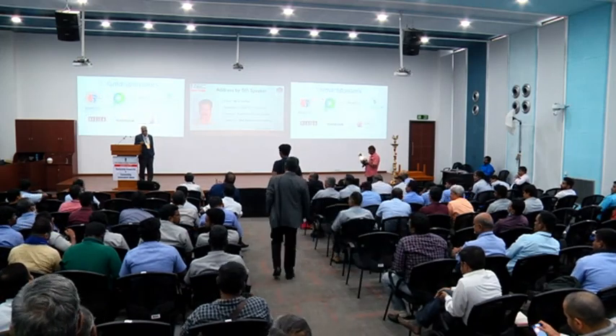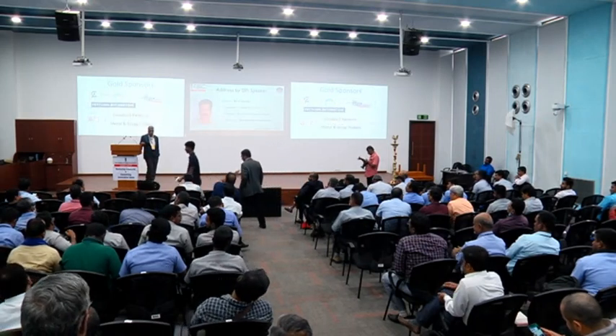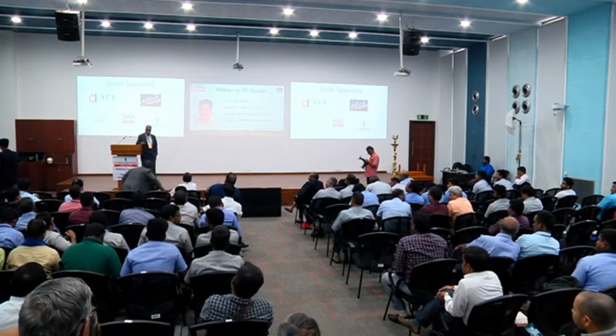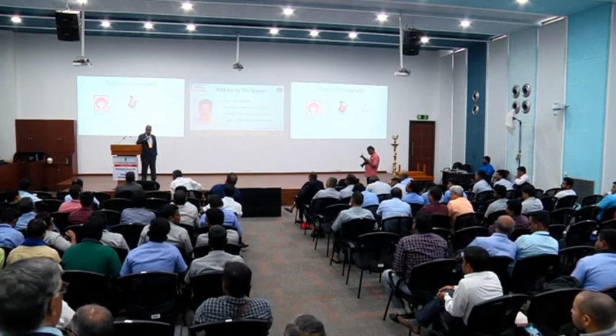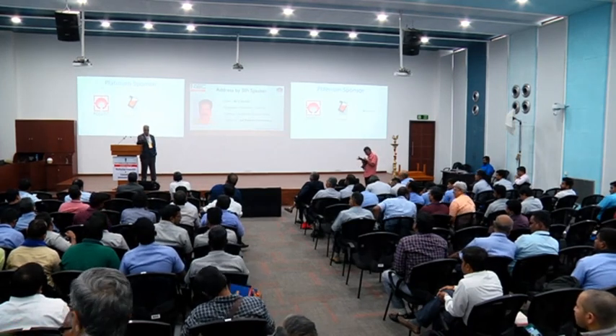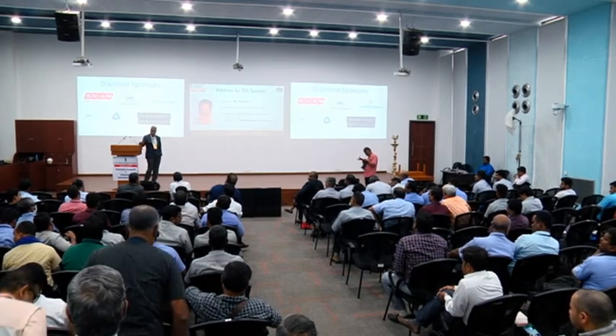Pneumatic system for AFS, from bunker to the silo to the mixer, there is a gradual deterioration in the AFS. How to control that? The sand delivered into the sand hopper, there you can put the extraction and remove the fines content, and remove all the dust it flows.